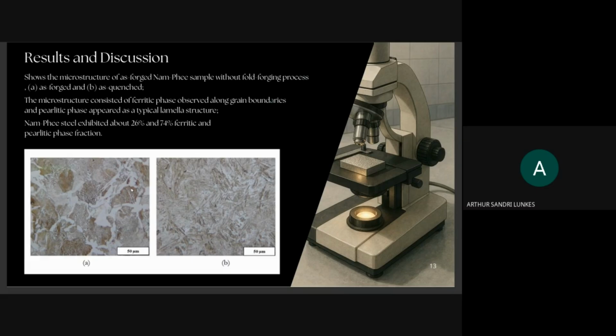Now we start talking about the results of the article. This picture here represents the Nam Phe steel without the fold forging process. Picture A is the forged, and picture B is the process with quenching. So the microstructure here consisted of ferrite observed along the grain boundaries, and pearlite appears as a typically lamellar structure. So this one here we have martensite, but this one here we have ferrite and pearlite. Okay. For the Nam Phe steel, we have around 26% and 74% ferrite and pearlite phase fractions. We will explain this in a few slides again.